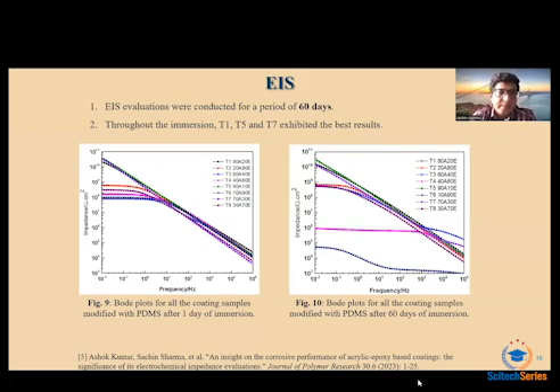Right. So similarly, we also captured the results at the end of the immersion period, which was at the 60 days. And here again, we could see that T1, T5, and T7 still maintained excellent barrier property against corrosion, exhibiting Z impedance values ranging between 10 to the power of 10 to 10 to the power of 11. So which means that even after 60 days, it provided a tortuous pathway for the electrolyte ions to penetrate through the coating to the metal substrate. So it's taking a much longer time to reach the metal surface.